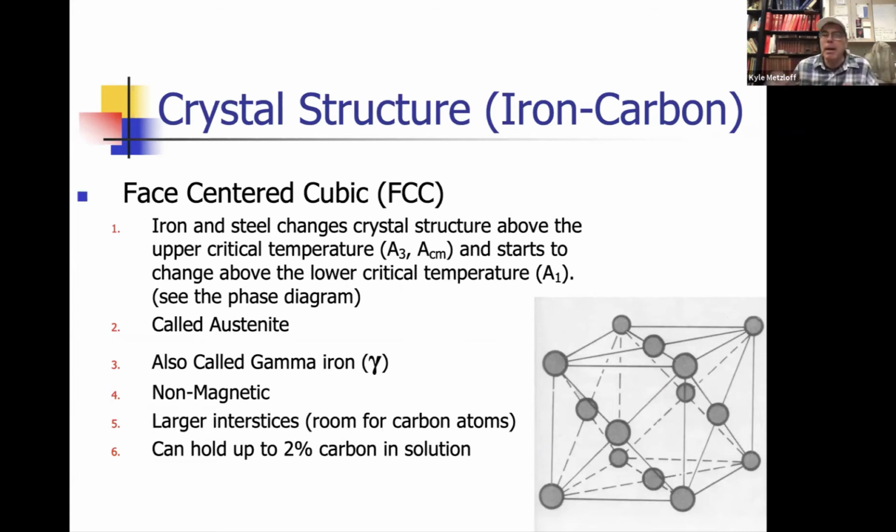They actually literally pack, that's one of the ways you can pack your piece of steel in charcoal and put it in a furnace and heat it up to high temperatures in a little metal box or something. And then there's a little bit of a chemical reaction that happens at the surface with carbon monoxide, but essentially the carbon dissolves into the surface, okay?